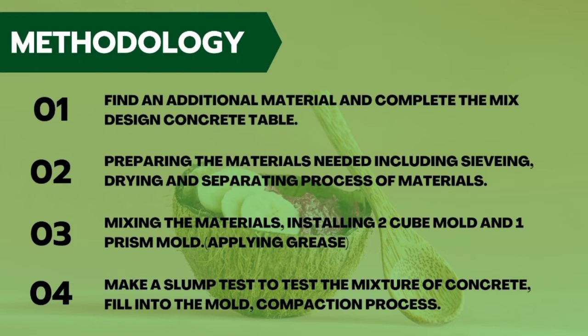For the fourth step, we had to perform a slump test. The function of the slump test is to test the workability of the concrete mixture. After the slump test, we determined whether our mixed concrete design was successful. If successful, we proceeded to fill the mixture into the mold and carry out the compaction process using the vibrating machine. If the slump test failed and did not achieve the required value of 20 mm, we had to mix the mixture again.